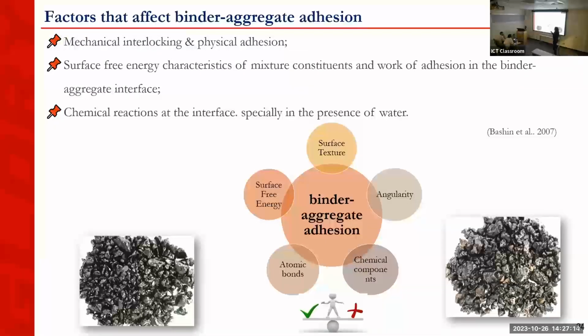We tried to evaluate the binder aggregate adhesion through different perspectives. Binder and aggregates interact with each other, and the adhesion can be due to physical interactions, physical adhesion, thermodynamic interactions, thermodynamic adhesion, or chemical interactions, chemical adhesion. All those things can contribute to a good binder aggregate adhesion. So, talking about balanced mix design, I try to use the same concept, to balance chemical, thermodynamical, and physical properties of the slags to have a better adhesion.